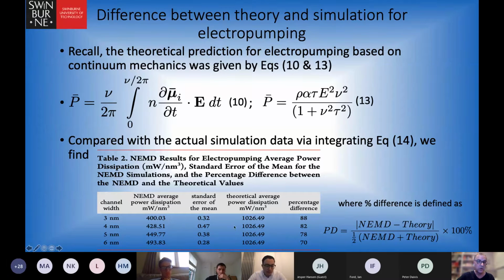So they always said that their power dissipation was very high, and it is. But when you look at what you actually get, you're about 2.5 times smaller. So it's not as bad as what they first thought. And clearly, as you increase the channel width, the agreement becomes better, which is what you would expect. You would expect the theory and the actual simulation to converge in the limit as the channel width goes to infinity.